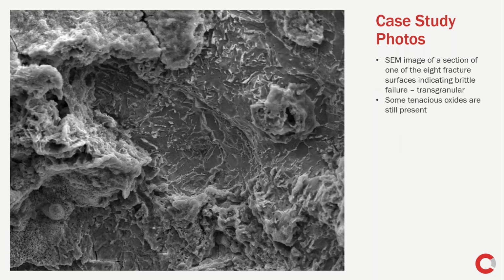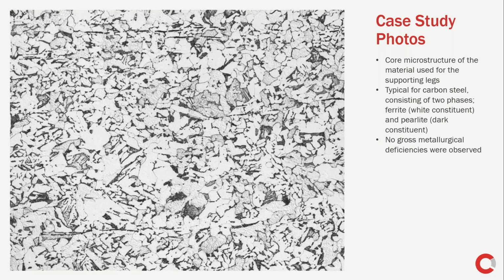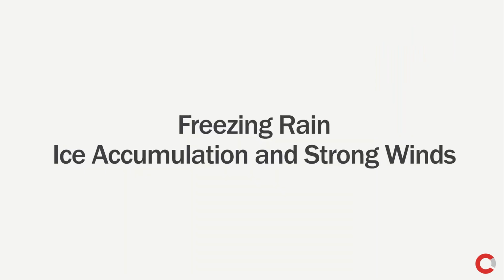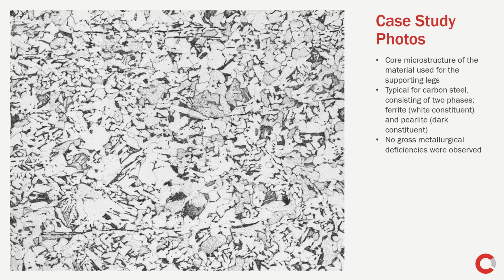We also looked at the microstructure. Every material is made out of grains, like ingredients in a food. You put ingredients together and you get the final mixture. Same thing applies to materials and alloys, and carbon steel is one of the simple alloys, consisting of 2 phases. There was nothing wrong with the microstructure. No gross metallurgical deficiencies were observed. So there was nothing wrong with the material. However, it failed in a brittle manner, which it shouldn't.